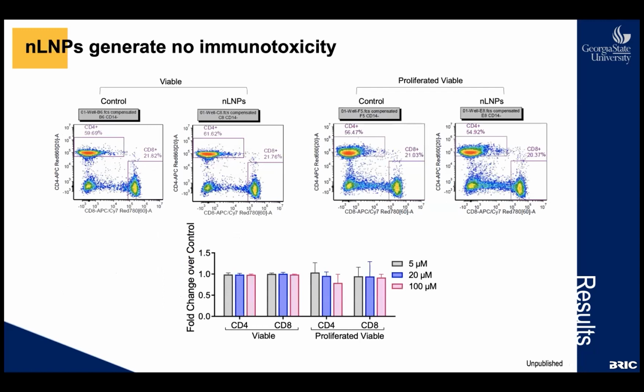And additional immunotoxicity was tested in vitro. The purpose of this study was to evaluate the effect of lipid nanoparticles on human CD4 and CD8 T cell proliferation after in vitro culture of PBMC. Cells were treated with the lipid nanoparticles for 4 days, and they were collected and stained with antibodies to be evaluated with flow cytometry to measure the percentage of CD4 and CD8 T cell populations. As we can see in this graph, the population of CD4 and CD8 is no different from the control group for both viable and proliferated viable experiment groups. And the bottom graph is the quantitative measure of the images above.